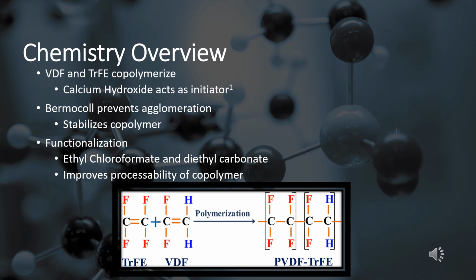So let's go ahead and take a look at a deeper dive of the production chemistry of PVDF-TrFE from vinylidene fluoride and trifluoroethylene. The first step involves the reaction between VDF and TrFE in the presence of calcium hydroxide and ethyl hydroxyethyl cellulose, which in our case is our commercial Bermocoll, as a stabilizer. This process will be our copolymerization and will result in the formation of a copolymer of both VDF and TrFE. The copolymerization reaction can be initiated by various methods, such as chemical initiators, radiation, or heat. In this case, our calcium hydroxide will act as a base to initiate the reaction between VDF and TrFE, while our Bermocoll just stabilizes the resulting copolymer.